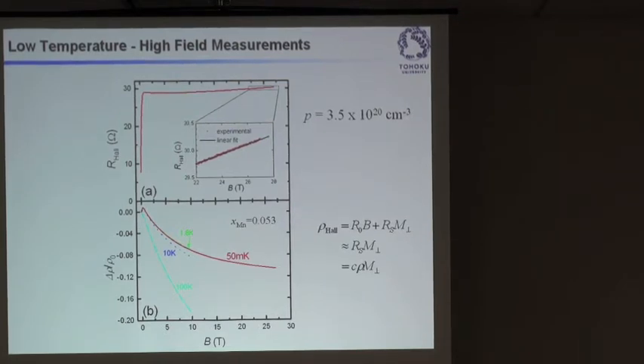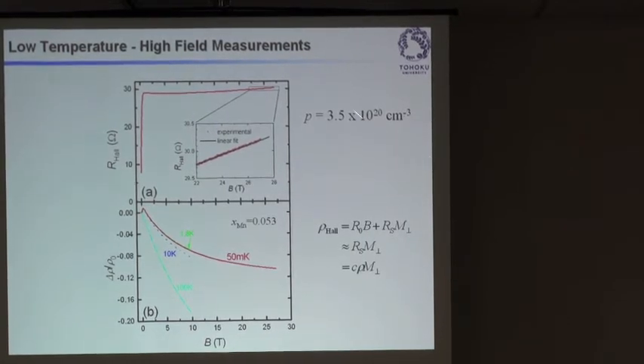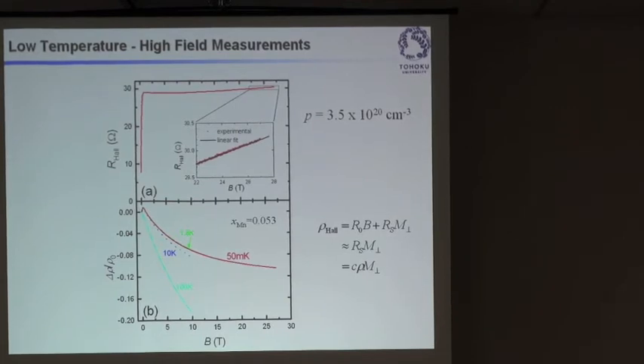And from this, we have determined that in this particular sample, we have 3.5 times 10 to the 20 carriers, and the conduction type is p-type, so we have holes, in accordance with the fact that manganese in gallium arsenide is an acceptor. This particular material has 5.3% manganese, and we get 3.5 times 10 to the 20 per cubic centimeter holes. And the numbers don't match. If we assume that we have a very simple acceptor in gallium arsenide, we should expect 5.3% equivalent number of holes. But that's three times more than this number. So we only see 30% of activity in terms of acceptor activation.